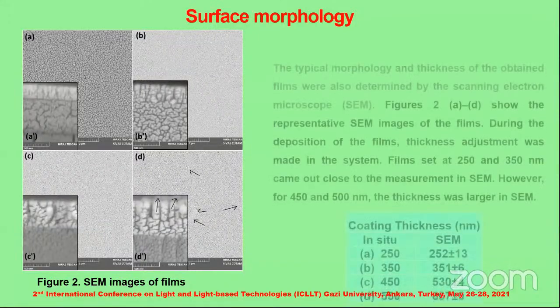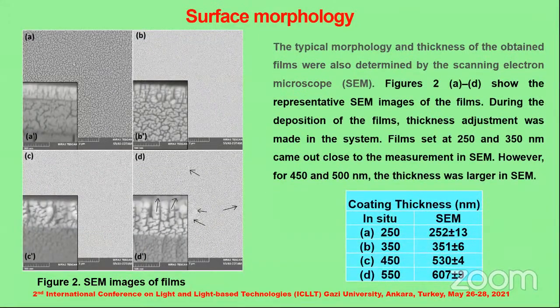Surface morphology. The typical morphology and thickness of the obtained films were also determined by the scanning electron microscope, SEM. Figure 2 A to D show the representative SEM images of the films. During the deposition of the film, thickness adjustment was made in the system.